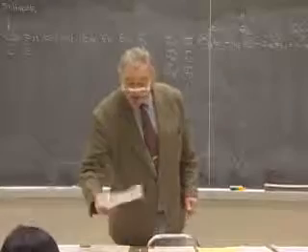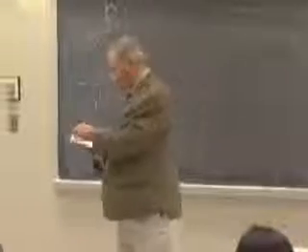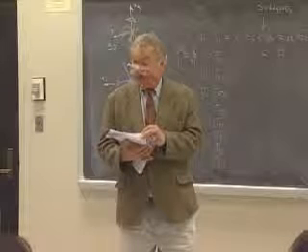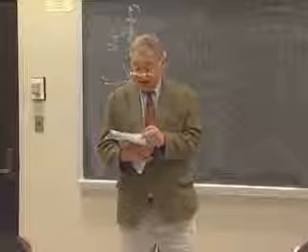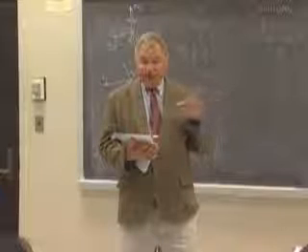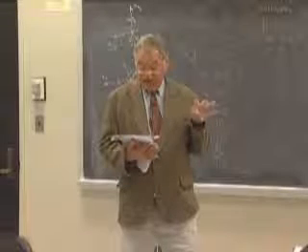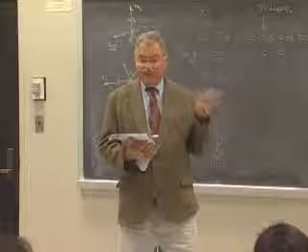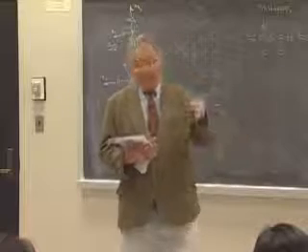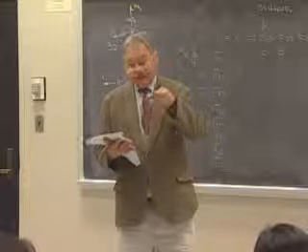How about symmetry restrictions? Holy mackerel. Transformation of 81 different elements. Well, in order to do the tensor transformations, you have to go to the full four-subscript notation. Only then is a law of transformation defined. 4th rank properties are even tensors, so mercifully there are not as many different possibilities. All point groups that differ by presence or absence of inversion have exactly the same form of the tensor. So symmetry 2, m, and 2/m look alike. Symmetry 222, 2mm, and 2/m 2/m 2/m look alike.